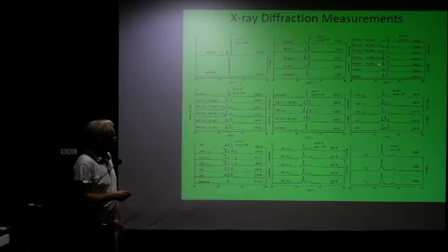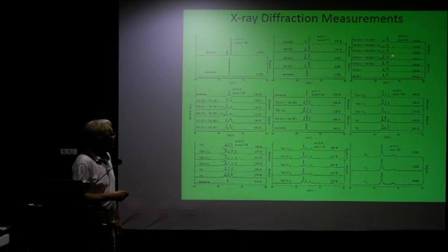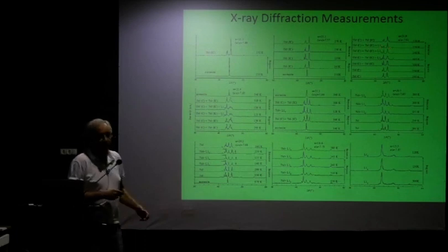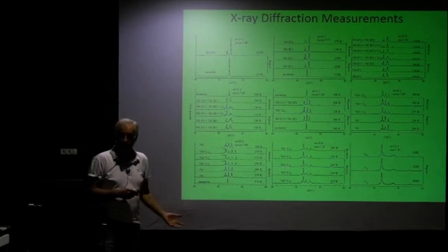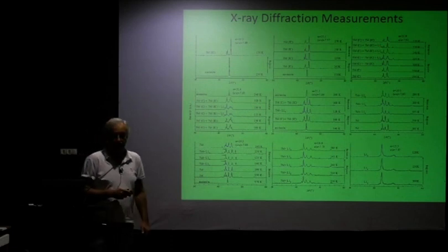And then you go into cases where, at room temperature, it's already Martensite in this sample, for example, and then you go down, cooling down to 200 Kelvin, and then you have a 7M coming out, you have L10 sneaking out, and when you go back, you see a hysteresis. So at 200 Kelvin, there was no L10, but on going back at 220 Kelvin, you have the L10 stuck in there. So it's hysteresis, okay? And you have to go to a higher temperature before you can get rid of the L10 over there.